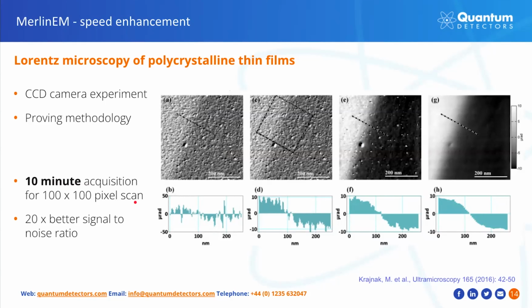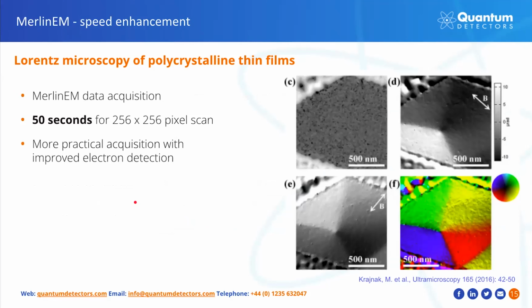but the experiment helped us to develop a methodology with which we can improve signal-to-noise ratio by the factor of 20. Of course, once we have installed MerlinEM detector in Glasgow, the acquisition of such data became much more practical. Not only the same experiment was much faster, but also we could take much larger scans and therefore analyze larger sections of the sample. I'll come back to this a little bit more in the following application section and explain the methodology behind the signal-to-noise improvement.